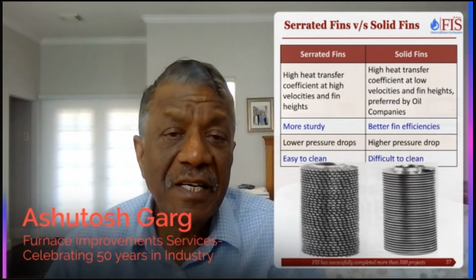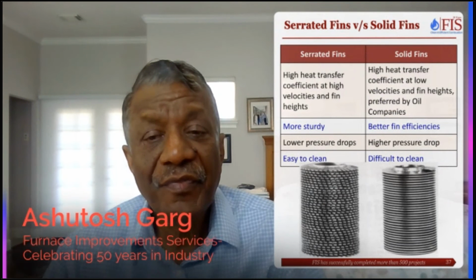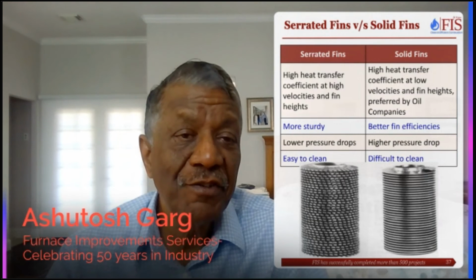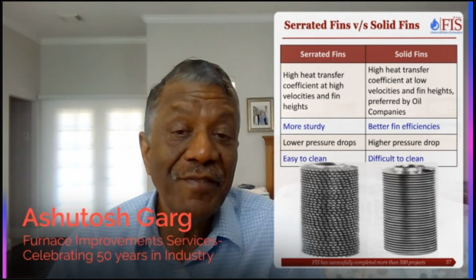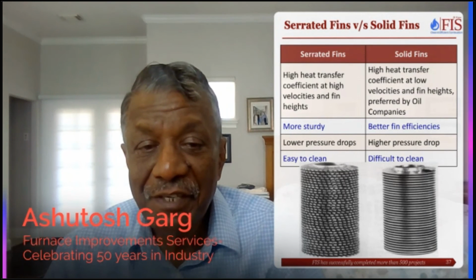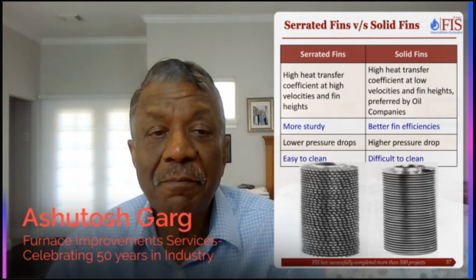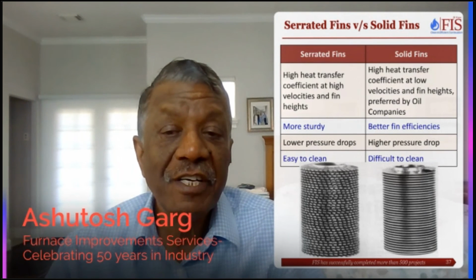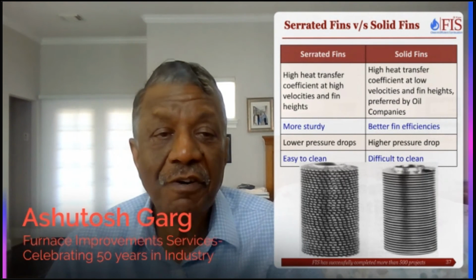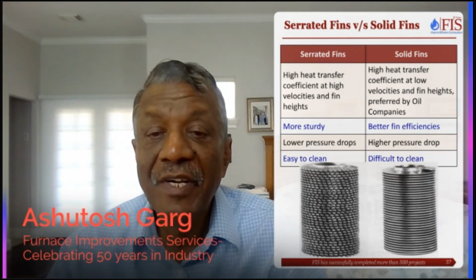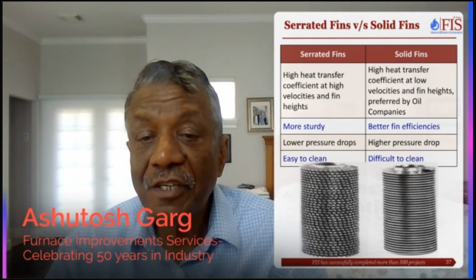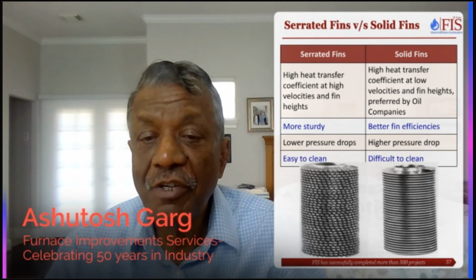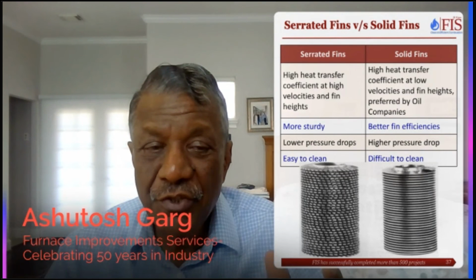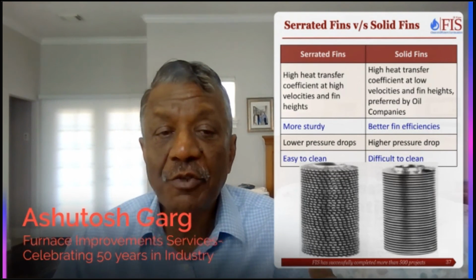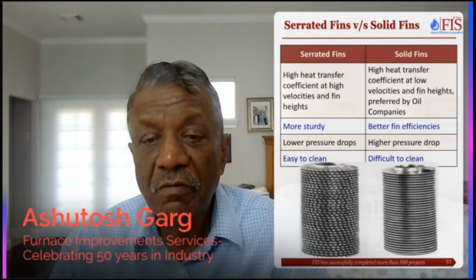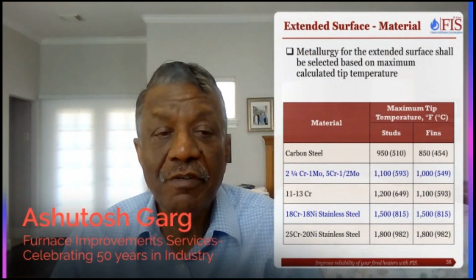Similarly, in fins, there are two types of fins, serrated fins and solid fins. Serrated fins have high heat transfer, lower pressure drop, easy to clean, but somehow the oil companies have preferred solid fins. The end users have always preferred solid fins, so solid fins are the standard in industry. Another reason of using solid fins is solid fins can be made out of thick material as high as 0.2 inch or so. And once you use thick material, you can get better efficiencies. So solid fins are the de facto standard for refining industry.